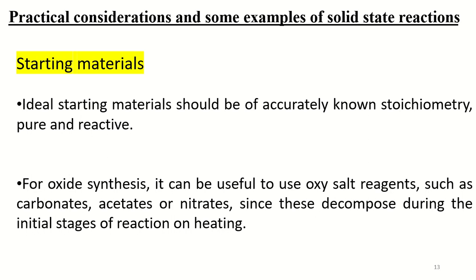For oxide synthesis, it can be useful to use oxysalt reagents such as carbonates, acetates, or nitrates, since these decompose during the initial stages of reaction on heating.